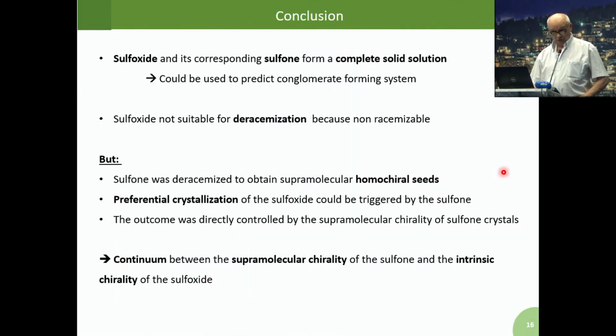So, the conclusion of that piece of work is that the sulfoxide and its corresponding sulfone can make a complete solid solution. Okay? And this could be used. So what I want to do now is to have a survey on the Cambridge Structural Database and to see all the different sulfones which crystallize in a chiral space group. Then, of course, that will be a pretty good indication that the corresponding sulfoxide could also crystallize as a conglomerate.